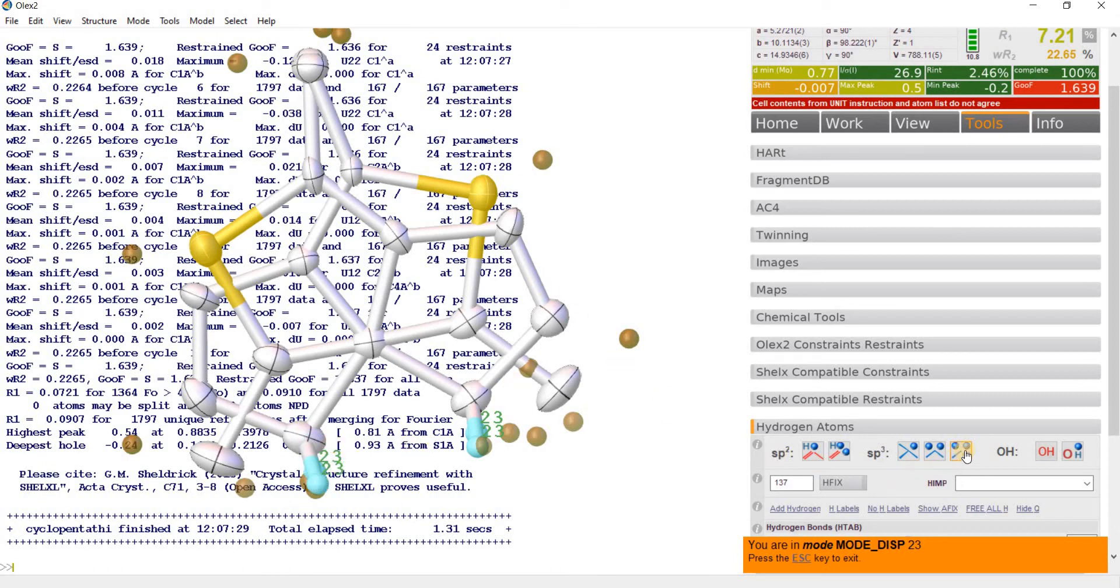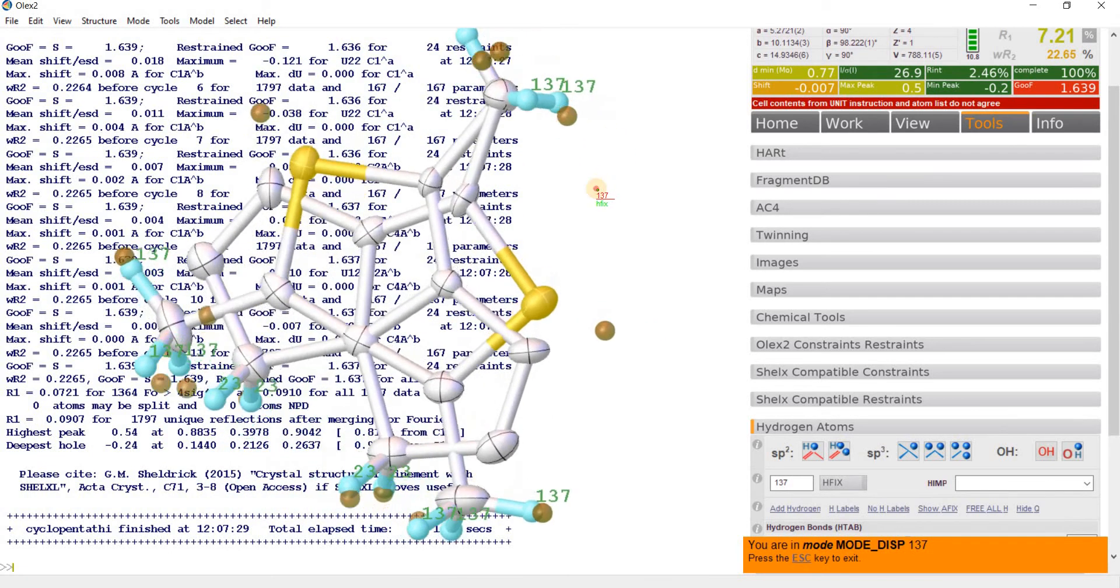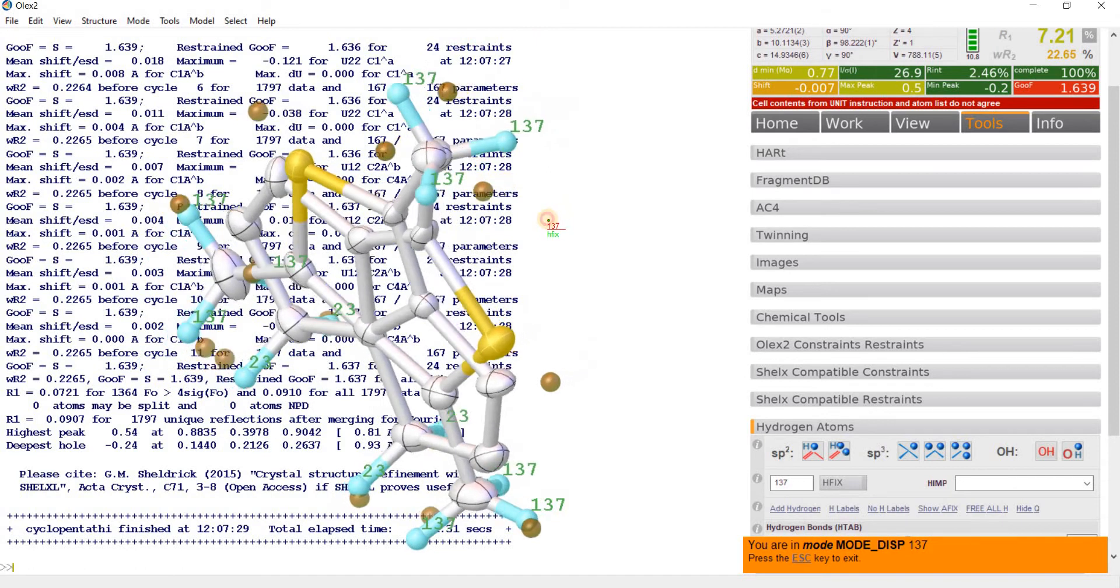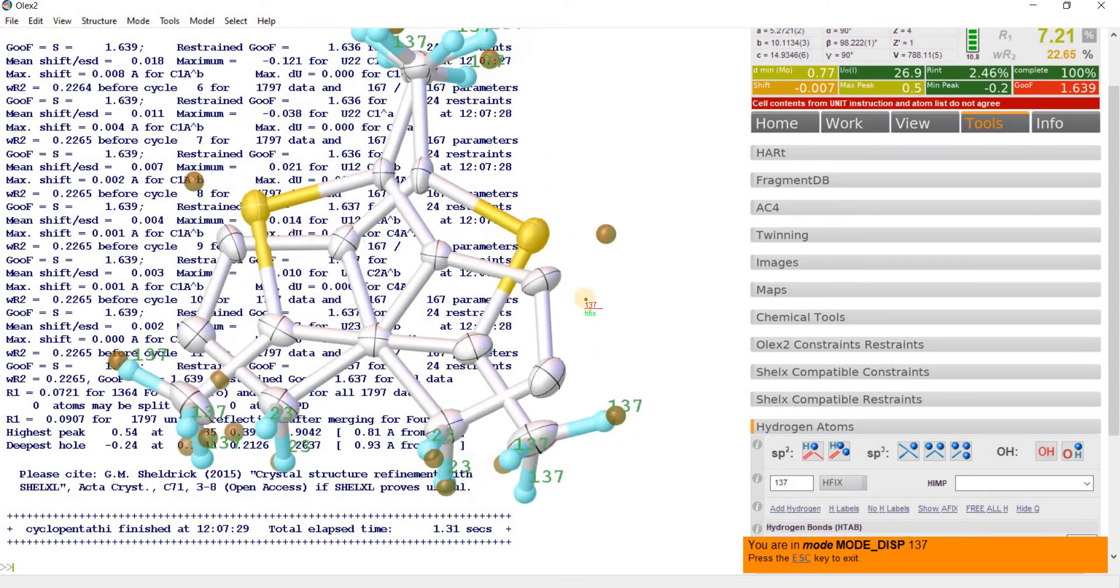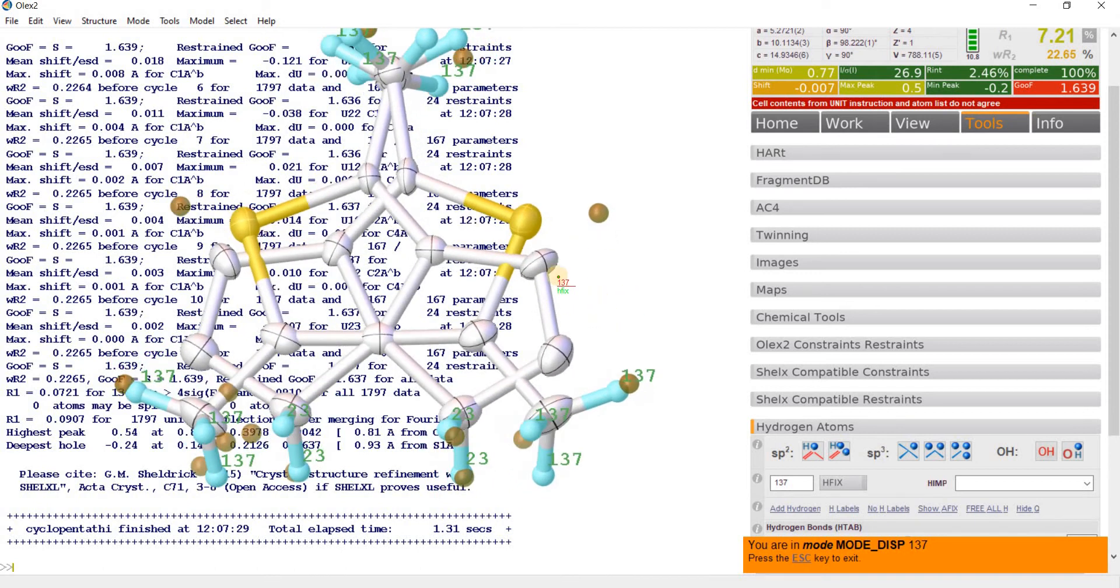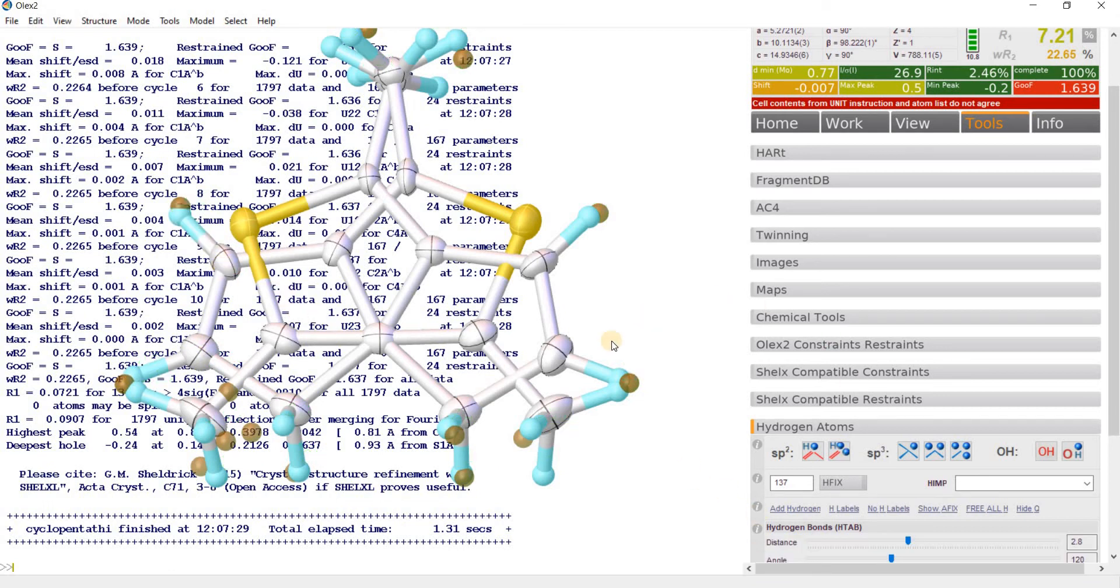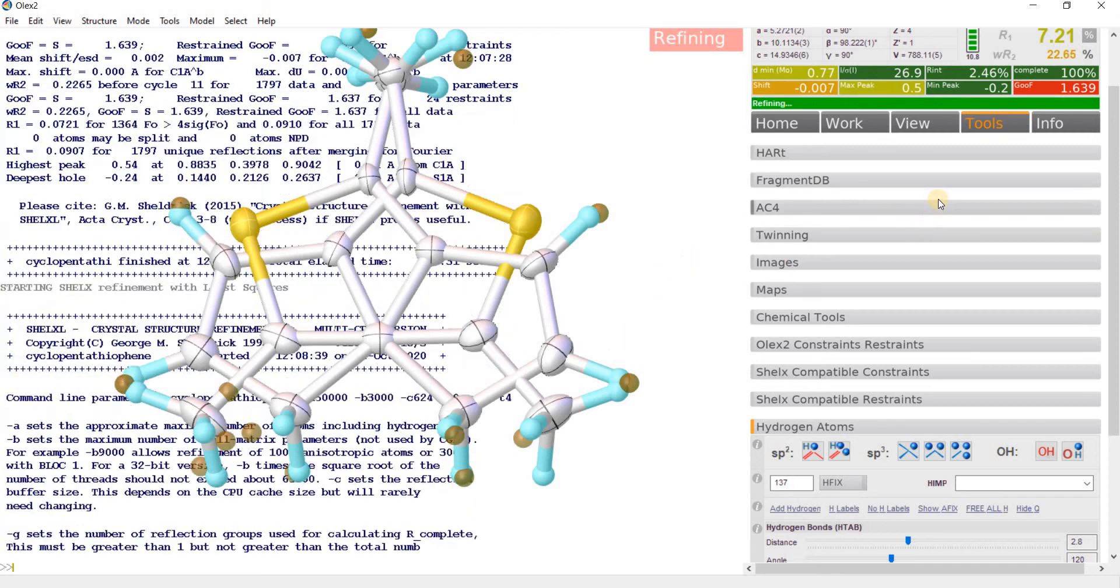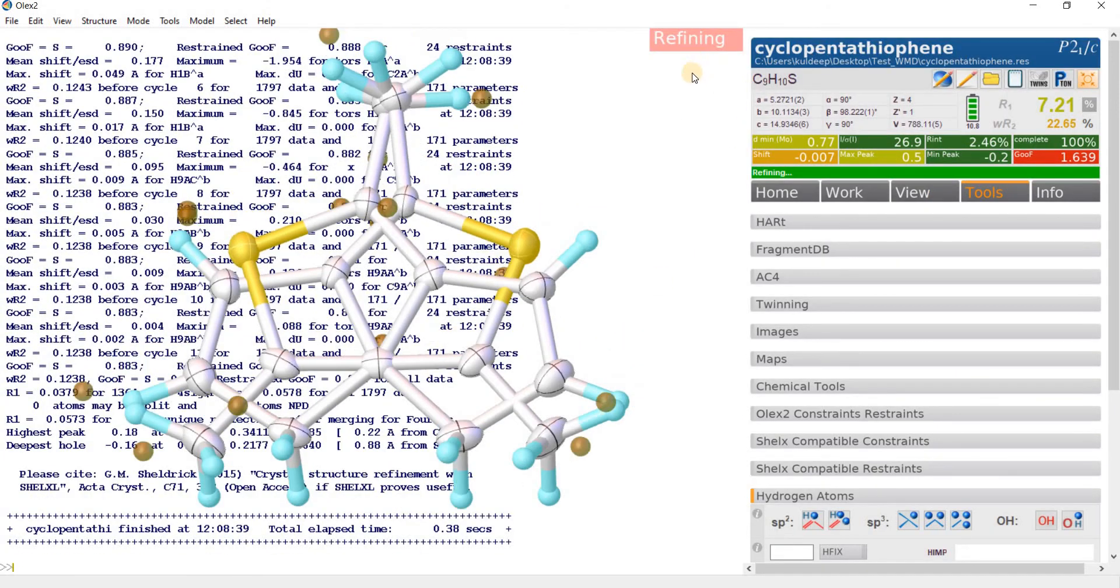Now they are getting somewhat better. The next step is adding hydrogen. For that purpose you can automatically add hydrogen by pressing add hydrogen, or you can do it manually. Let's do it manually. Go to tools, hydrogen atoms. First go to SP3 methylene. This is methyl. Then go to methyl. This one is methyl, this one is methyl. We are left with only aromatic hydrogen. Go to SP2 and click on the aromatic carbons.